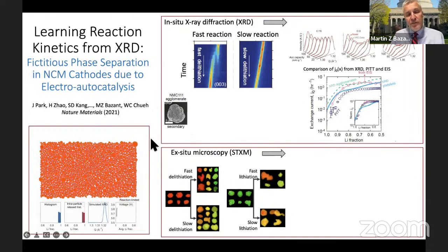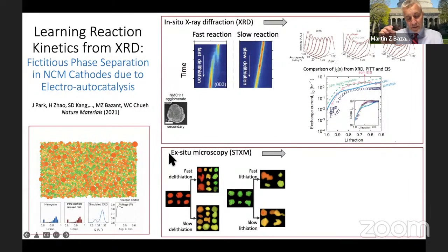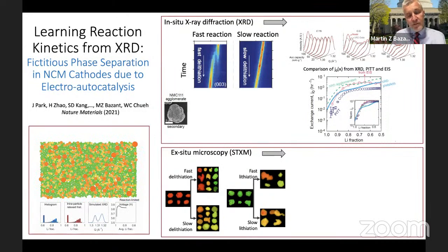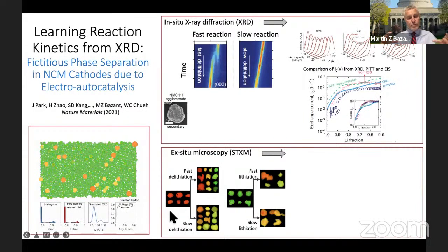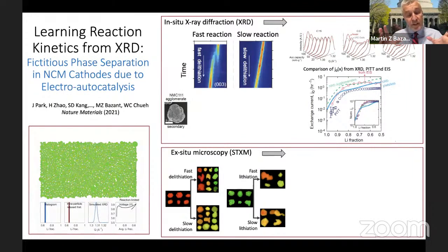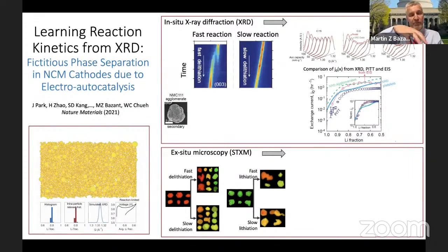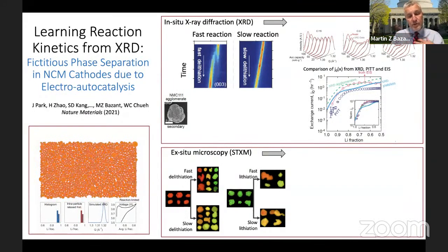And even with such results, we found that various reviewers and some colleagues were still very skeptical about this. The real key prediction, though, was not just to do constant current, but to do, for example, pulses or interruption of current. So if you do insertion of lithium at a constant rate, or extraction, let's say, and then you turn off the current. Somebody who believes this is explained by nonlinearities in diffusion inside the particles would have to say that there's a shrinking core of one phase being replaced by the other. So there are gradients inside the particles that are leading to this behavior. But we would say, no, it's from reaction kinetics. So the differences in concentration are between different places on the surface or between different particles.